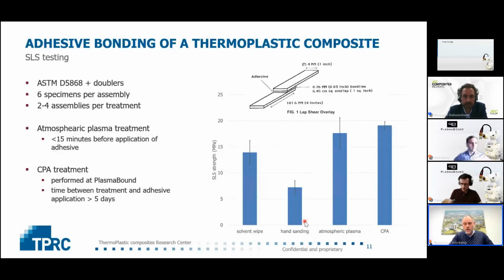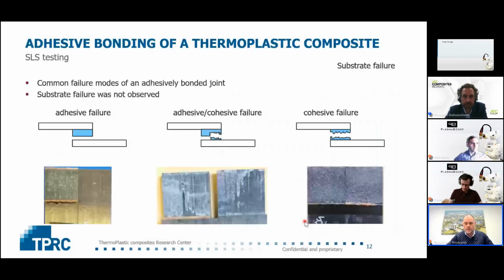It's not looking only at the lap shear strength values, but it's specifically looking at the fracture surface, which gives you more information. So we observed adhesive failure and cohesive failure and mixed mode. We did not observe substrate failure or fiber breakage.